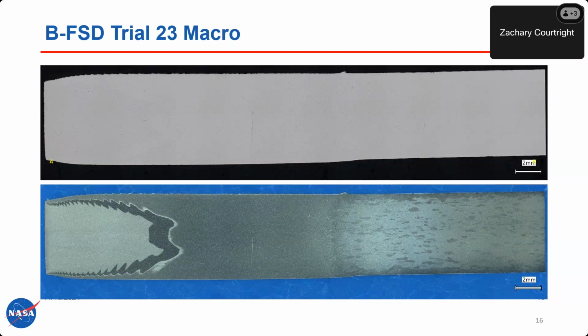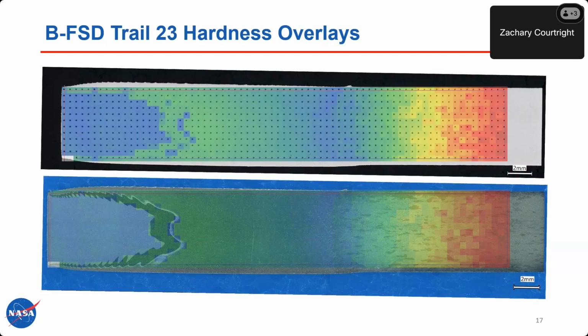And then the next slide shows a micro hardness map that we did, which basically aligns with what you would expect to see, pretty similar material property drop that you would see in any friction stir weld. So as you work to optimize, it's completely reasonable to assume that you could achieve 60 to 80% properties of what the original material was. But that kind of brings me to the point where, depending on the alloy, if you're familiar with friction stir welding, some would require some amount of post build heat treatment to get you back up to certain properties if you wanted specific properties.